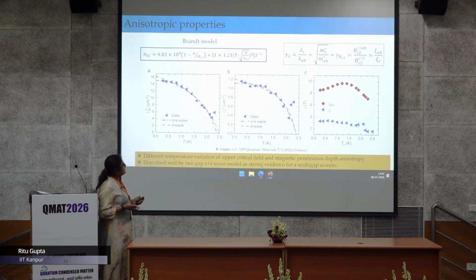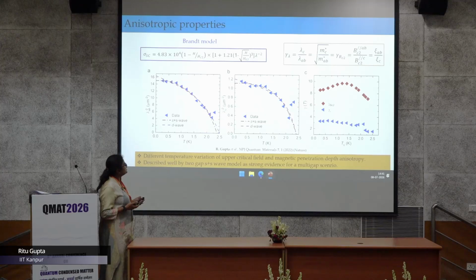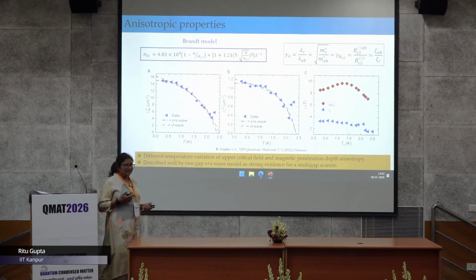Basically, within the Ginzburg-Landau model, the anisotropy in the penetration depth, which is nothing but lambda c by lambda AB, and the anisotropy in the upper critical field should both be equal for a single band superconductor. But here they show a different temperature variation, which further confirms the multiband nature of superconductivity. So the results shown here are at ambient pressure.